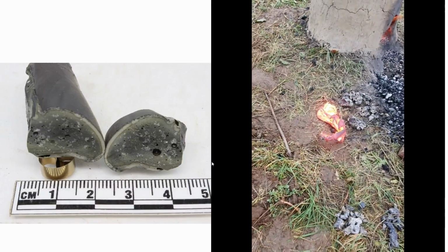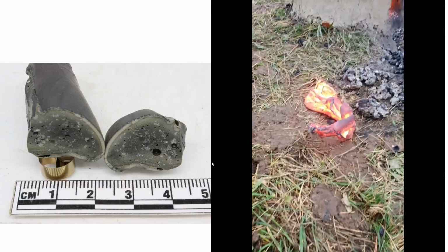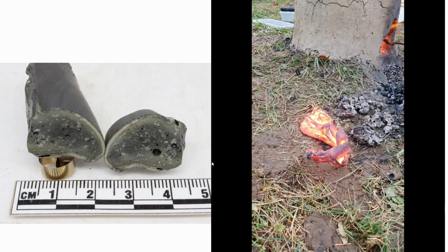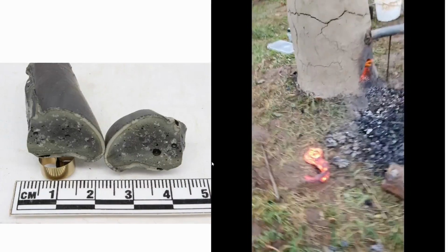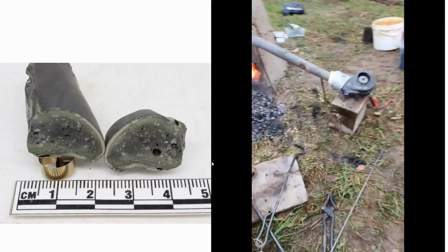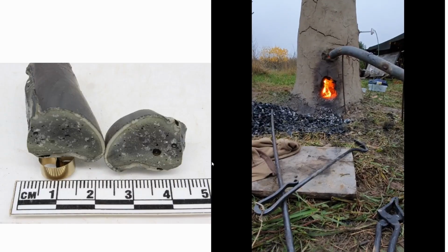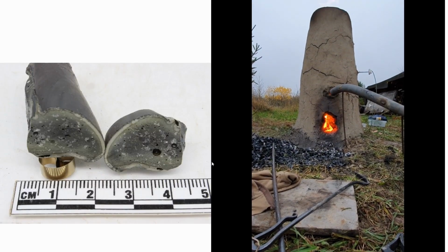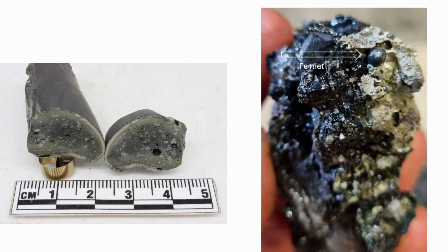While rapid air cooling contributed to this, the slag composition was likely the primary factor because the iron content in the slag was significantly lower than that found in archaeological slags. And speaking of metallic iron, smelting 11 kilos of phosphorus-rich ore resulted in only 3100 grams of phosphorus-rich iron in the form of such small pearls.